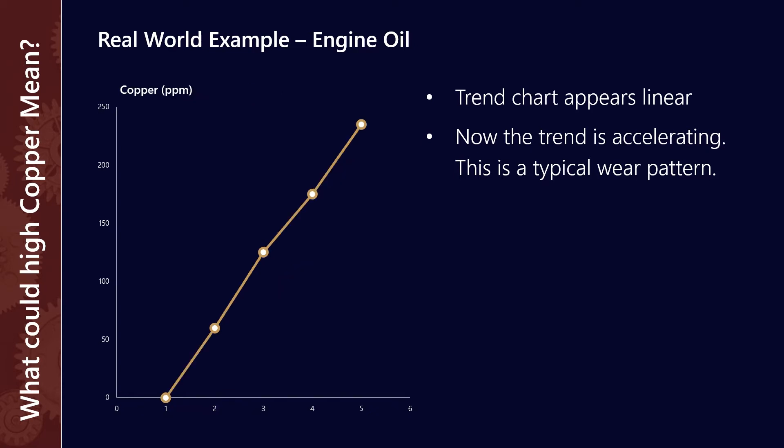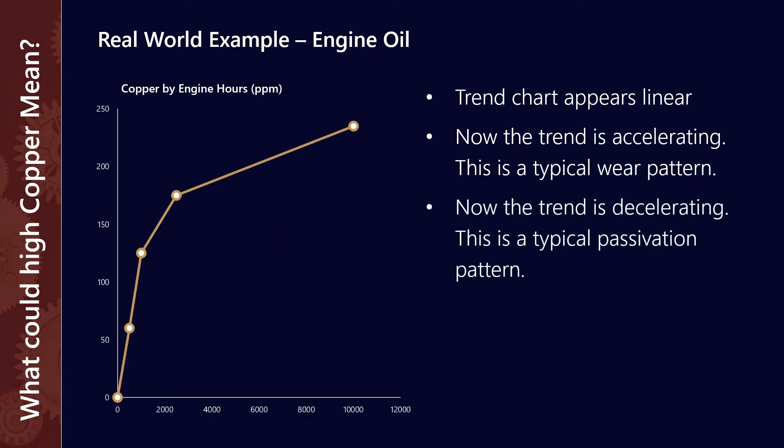But what if for example we could see the reverse trend. This is a decelerating trend which we say is typical of passivation. Now passivation itself not particularly harmful, very common to see it especially in new oil coolers. But we might want to confirm that it's passivation and that we don't have to take any interventions.